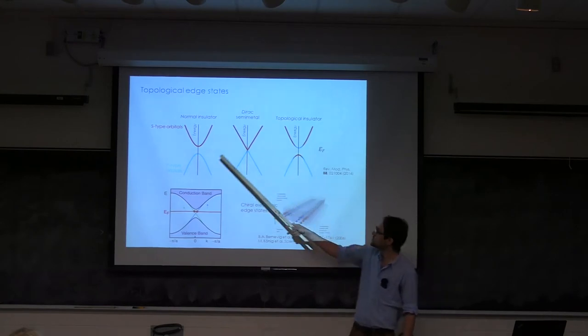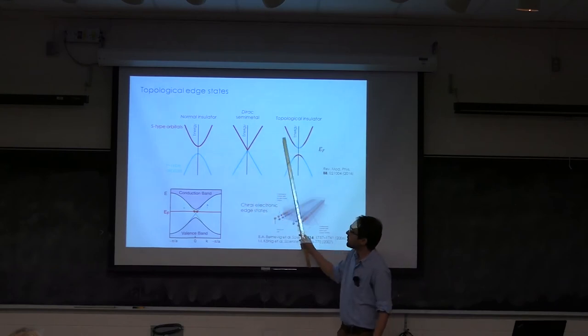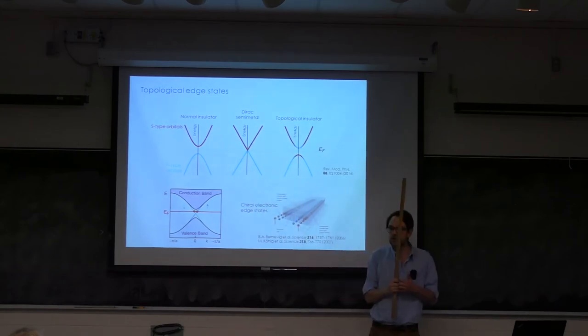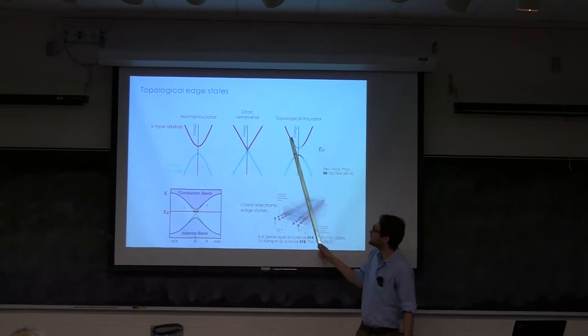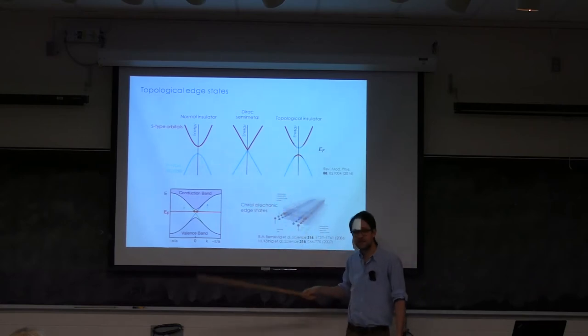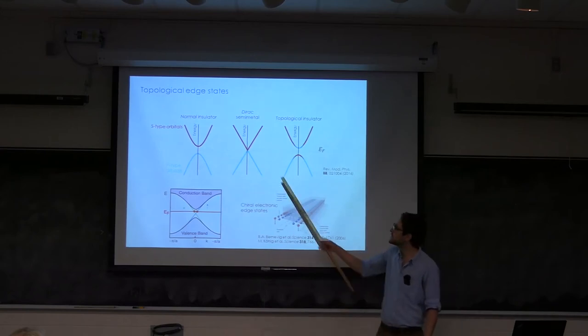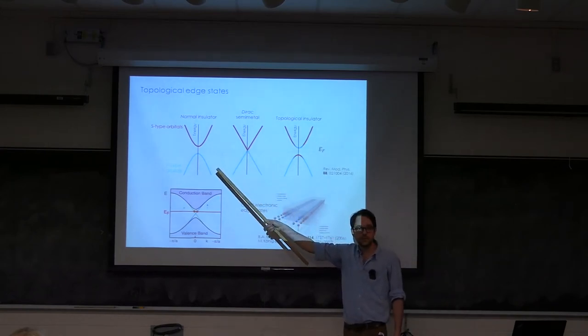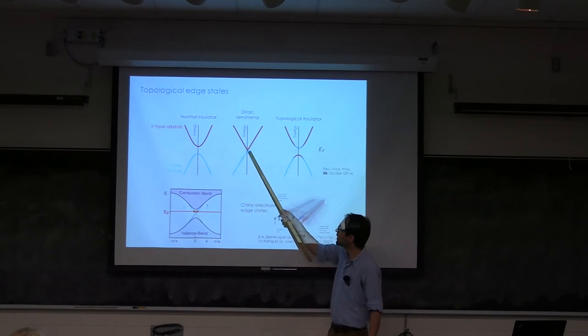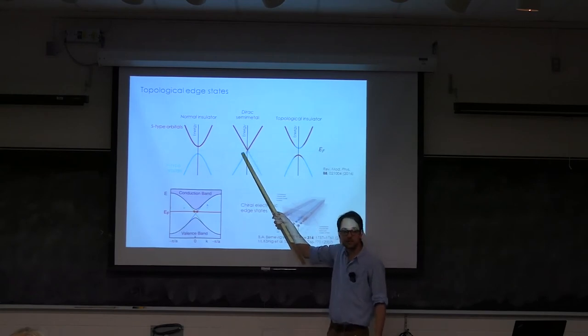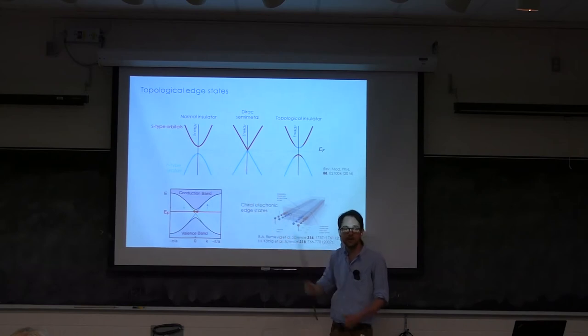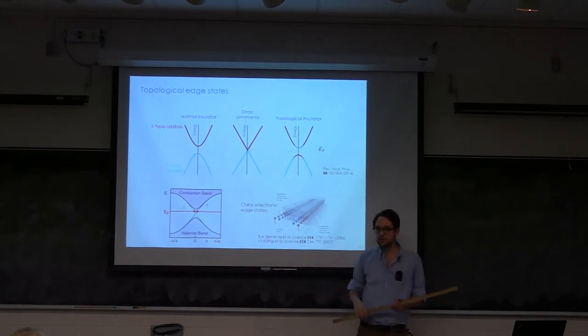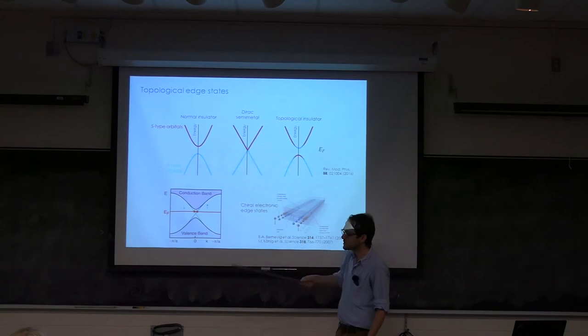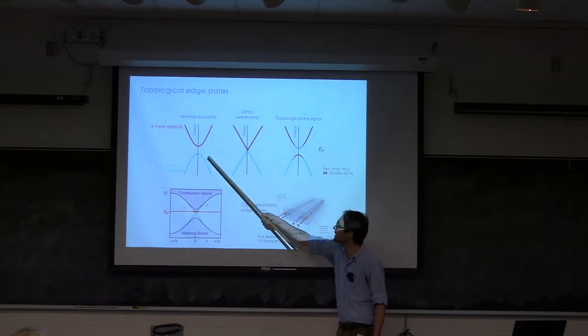So if you put these two materials together, the Bloch wave function will not be able to hybridize correctly. And in order to have a continuity in the wave function between these two materials, the system will have to close its energy gap and reopen. And as a result, at the interface, you will have localized modes that belong in a range of energy that is gapped on both sides. So we say that these states here are protected because they cannot scatter in the bulk. Even if your interface has some defects or some corners that the electron needs to move around, they cannot scatter.